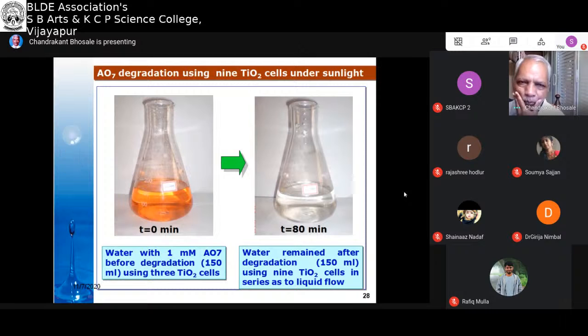If we have a dye, suppose this is acid orange 7 dye, and this dye is circulated through our 9-cell reactor, you see that this is the color before circulating, and this is the color after circulating through the 9-cell reactor for 80 minutes. What we notice is that the complete dye color is removed in 80 minutes. So this is the achievement of this reactor.